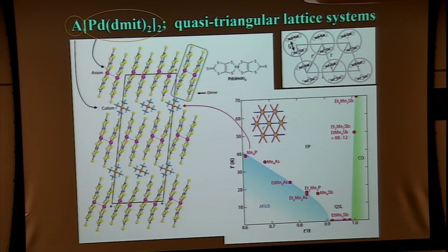like the BEDT-TTF, abbreviated to ET, as I talked about so far. So these are layered structures. This palladium DMIT2 forms a monolayer, and A is the insulating layer, where there's a cation. Many kinds of cationic molecular species reside in the insulating layers. So the layered structures are like the BEDT-TTF materials, insulating and conducting. But this material is a Mott insulator, so the whole system behaves like an insulator.